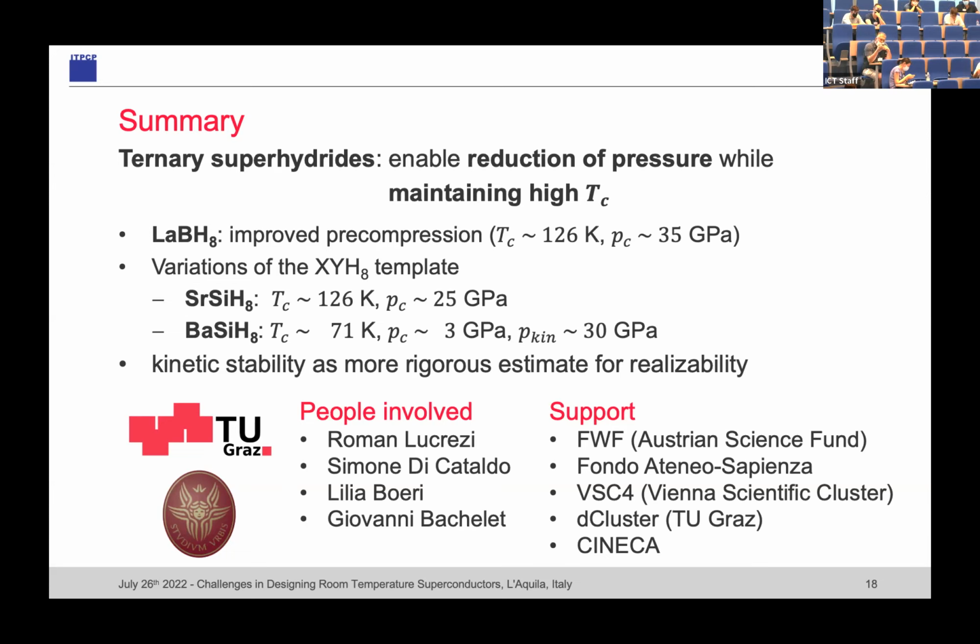Right. So the experiment that you try to describe is the one that one must do is, of course, as you say, prepare at high pressure, then decrease temperature to keep it as metastable as possible, right. Then go all the way to low pressures, but then inevitably you must warm it to see if it superconducts. Right. So to have a reference on the barriers that you showed, I'm not talking about entropy barrier, but a classical barrier for chemical reaction. It is normally assumed that in order to have a metastable system at room temperature, your barrier should be of the order of about 10 kilocalories, which is much more than the barriers you showed.